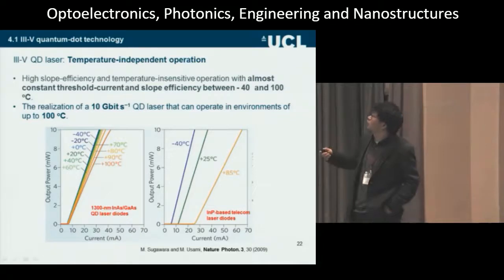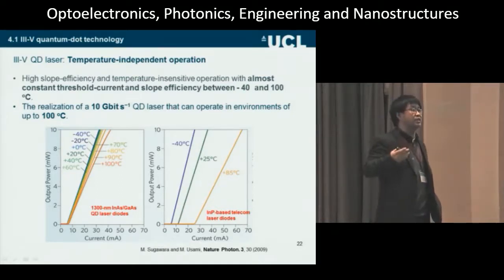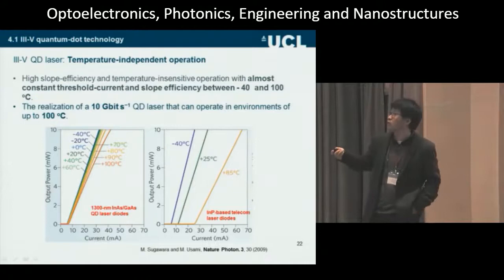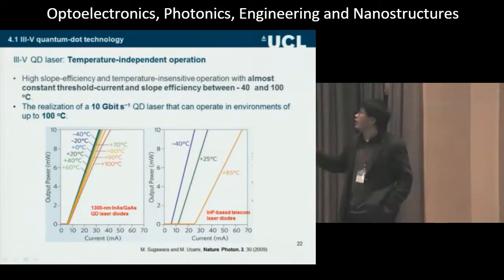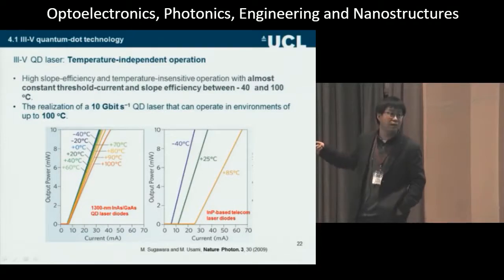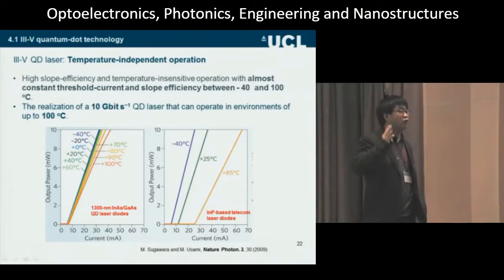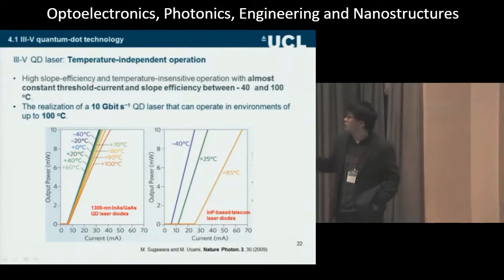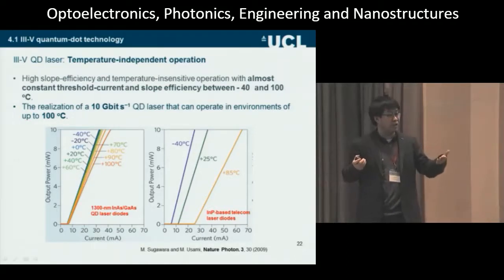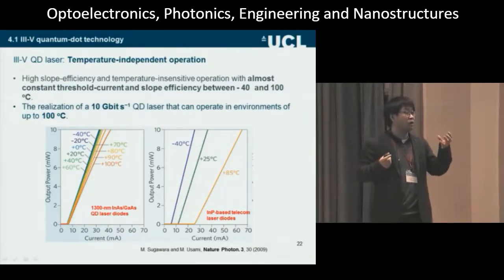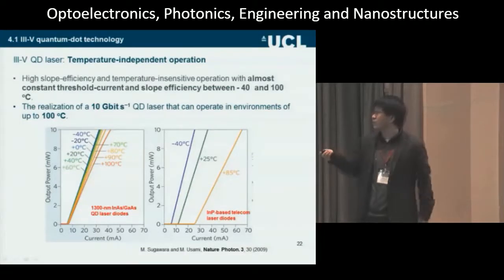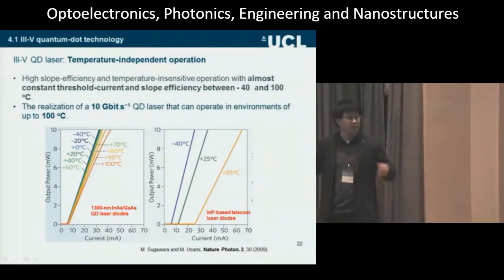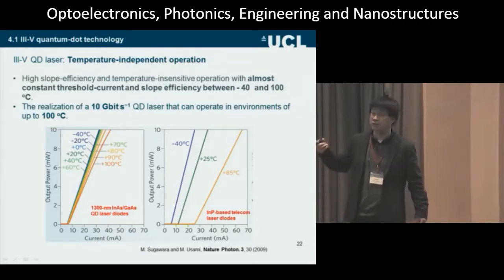So I show the best results, I think, from III-V quantum dot materials. This is from QD Laser. For these quantum dots, guys, from -40 to 100 degrees, the LI curve is almost the same. That means you have temperature-independent operation. This comes after 30 to 40 years of work from scientists all over the world, including Russia. And that's a conventional indium phosphide quantum well laser. You can see from -40 to 85 degrees, the LI curve is very different. That means for all your components with 1.55 micron operation, you need a cooler to make sure the laser operates at the same temperature to get the same performance. Actually, half the cost of your telecom components comes from cooling, just for the laser to have stable performance. But if you use a quantum dot laser, you don't need a cooler, so it's much cheaper. Also, they get 10 gig at room temperature and the laser operates over 100 degrees.